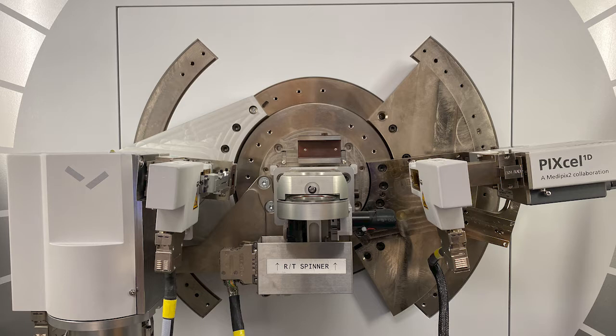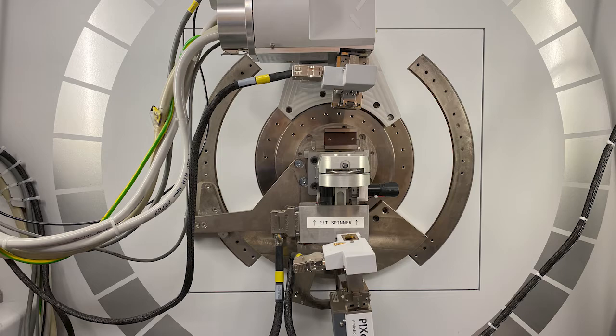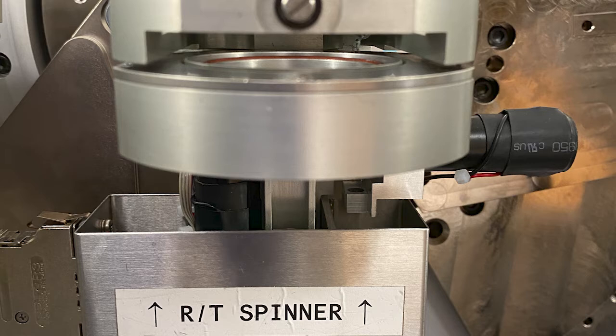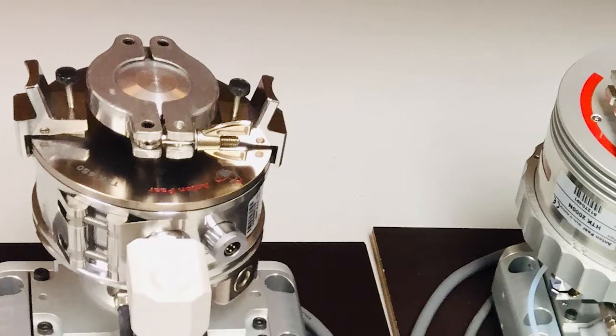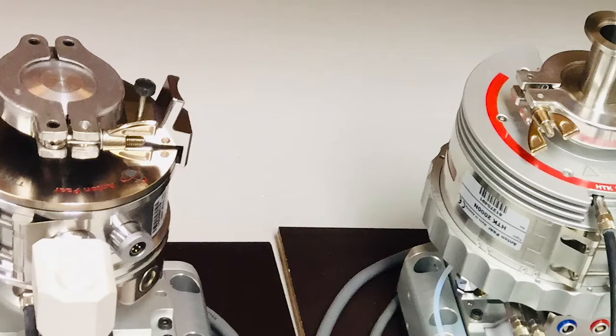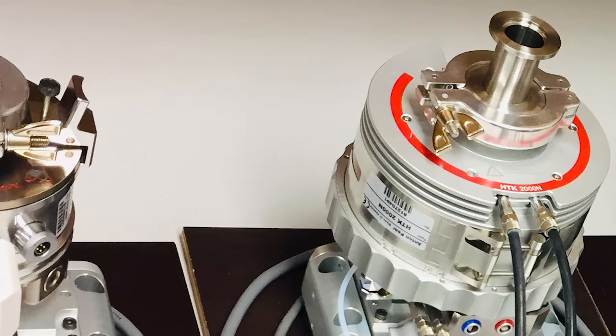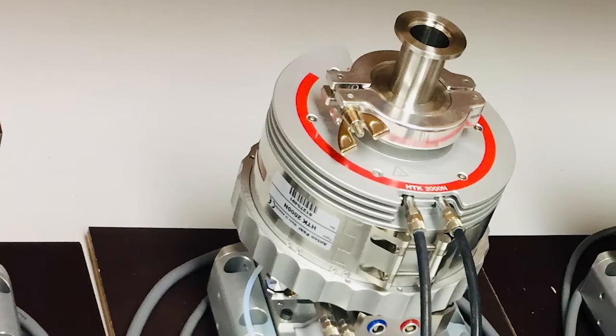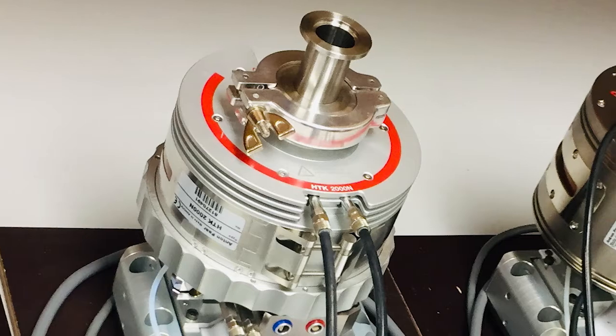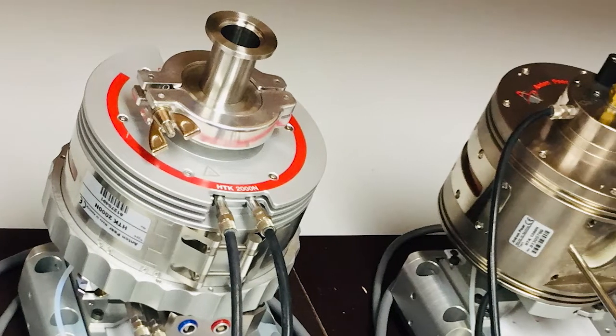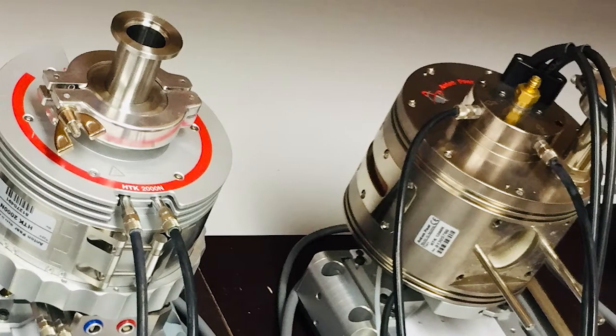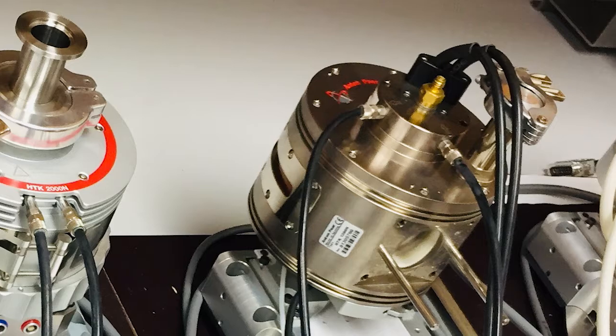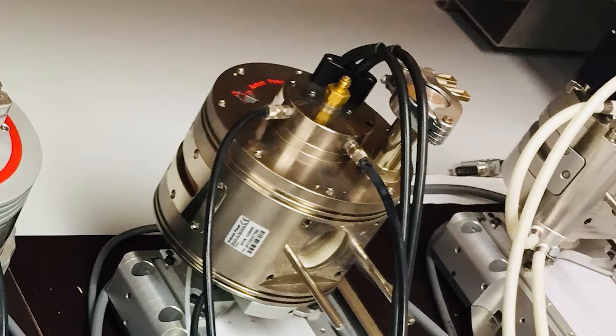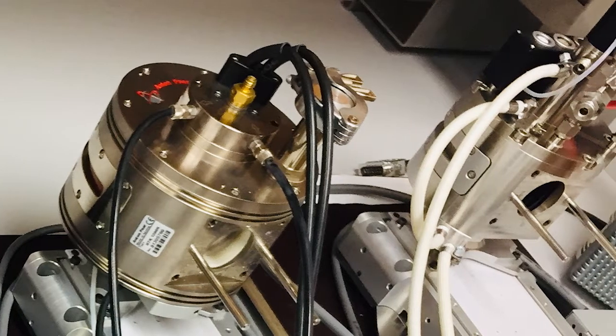The diffractometer can operate under two geometries, a reflection geometry and a transmission geometry. We have 5 different sample stages that can be installed on this diffractometer: 1 room temperature spinner stage and 4 non-ambient sample stages. These sample stages allow us to perform XRD measurements as a function of time and temperature in a very wide range of non-ambient environments. The operating temperature range we can use on this system is from -190 Celsius to 2300 Celsius. And we can use different environments in the non-ambient chambers, such as air, vacuum, inert gas, and reactive gas.